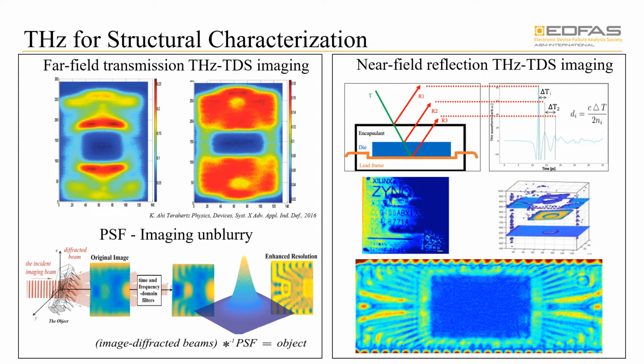Furthermore, we have the terahertz being used for structural characterization. It is a very attractive substitute solution to the SAM and X-ray, mainly due to its non-destructive contactless measurement. Here we can see that in the far-field transmission imaging, we are able to detect the internal structure differences between the authentic and counterfeit samples. However, the image resolution is very low, which is mainly because of the signal diffraction due to the propagation through free space. To eliminate these noises and the blurry images,